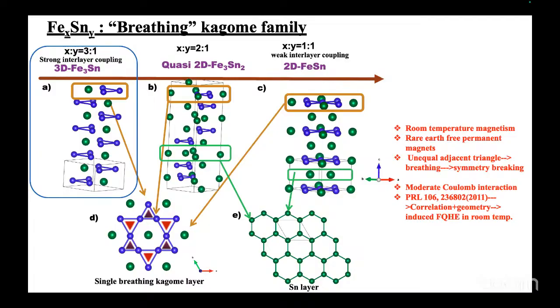So you said that you expected some large anomalous Hall effect. Why large? What do you mean by that? Because the band opening is different when we go from DFT to DMFT. The gap of the Berry curvature that we see is quite different as we move from DFT to DMFT. So we expect some kind of change in the anomalous Hall conductivity.